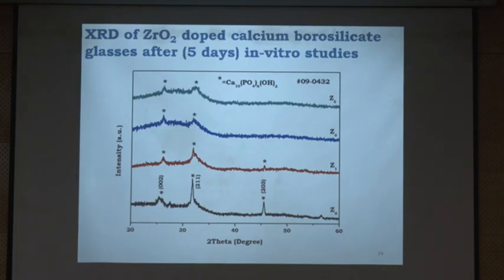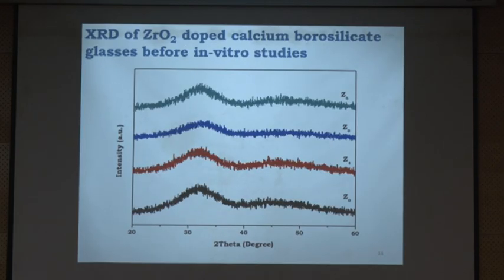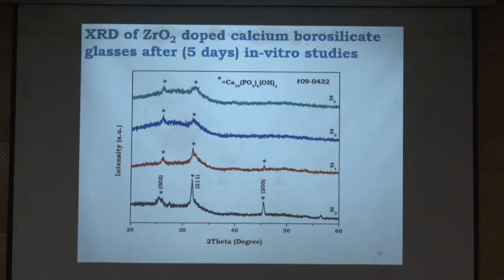Yeah, so this is before immersing the sample. So we have prepared the material, we have characterized the material, and we confirmed that the material is amorphous in nature, right? Then we immersed the sample in simulated body fluid, and we removed the sample after 5 days and characterized it. You can see the crystalline peaks at 002, 211, 203. So these are the crystalline peaks, related to calcium phosphate, the hydroxyapatite.